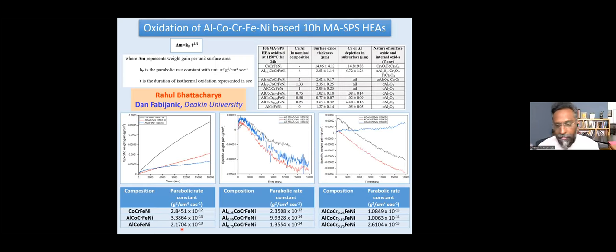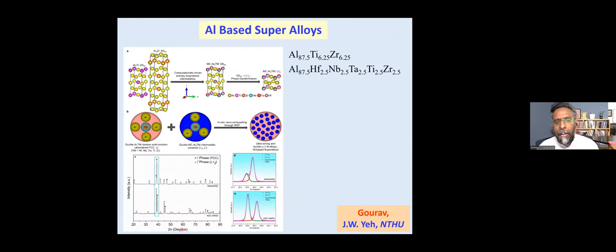And a lot of data, I don't want to bore you with that data. And one more very recent work is to ask, can we have similar superalloy kind of strength in even a soft material such as aluminum? So we call them aluminum-based superalloys. Aluminum alloys are usually known to have a reasonable strength at room temperature, but when you heat them, you lose all the strength. By the time you reach around 300 degrees centigrade, most of the aluminum alloys lose all their strength.